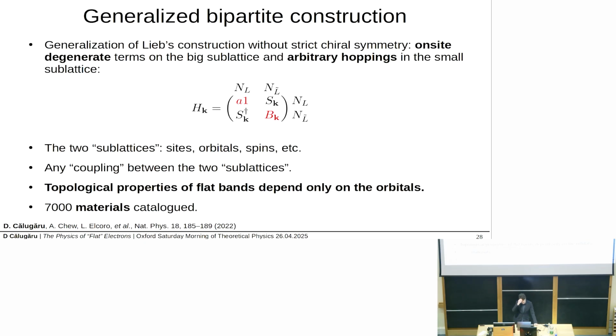Now, what we did in a recent paper was to generalize this and show some mathematical results which are very similar in spirit to topological quantum chemistry. What we essentially showed is that it doesn't matter how you couple these 2 sublattices. The topological properties of the bands only depend on the atoms of the two sublattices. And actually, after our study, a different team used these same concepts on all known materials and identified 7,000, that's 7 times 10 to the 3, materials that have flat bands and that you can actually synthesize in a lab.